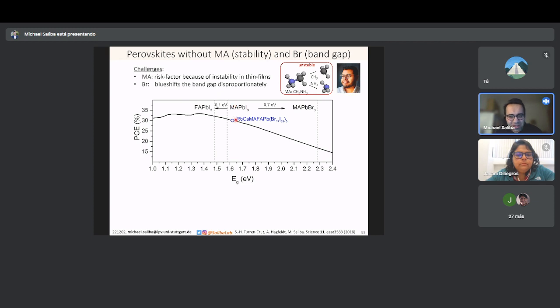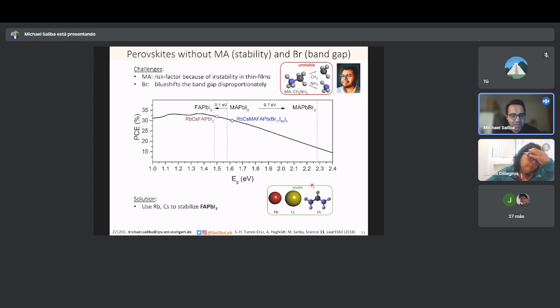So the target was to remove methylammonium for stability reasons and bromine for band gap reasons. And here on this Shockley-Queisser graph, essentially what we tried to establish was FAPbI3 only using rubidium and cesium. No unstable methylammonium, no bromine in order to stabilize the yellow phase. Only rubidium and cesium iodide. So we worked on that rigorously.